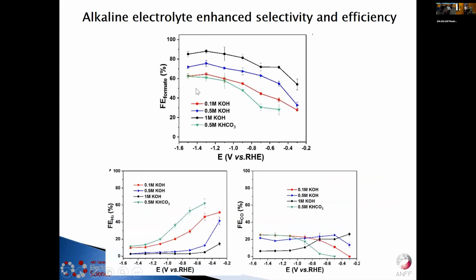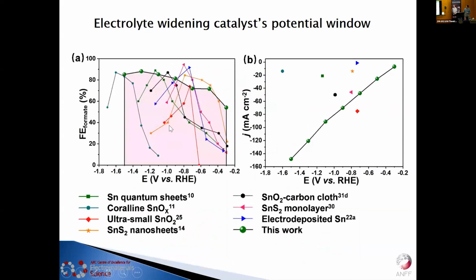But there's one real case for using an alkaline electrolyte. The first thing you can see here is that the suppression of hydrogen production is obvious. If you use, for example, 1 molar KOH, it really suppresses hydrogen production. And you can also suppress CO formation, and therefore you get quite a wide potential window across the range of investigated potentials. So if we compare with the other electrolytes, this really has a real advantage in this full cell, and we can widen the potential window, and also we can get quite a large current density.